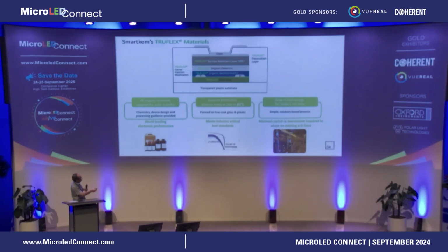But all the other layers, the base layer, which is a cross-linked polymer, semiconductor layer, surface electrode treatments, dielectrics, sputter-resistant layers, and passivation layers, are all our own chemistries and tuned for particular reasons to give good device performance. These are made and formulated in volume that can be supplied to display manufacturers in up to roughly 3.5 litre quantities in a bottle, and we can supply up to a couple of thousand litres a month if necessary.